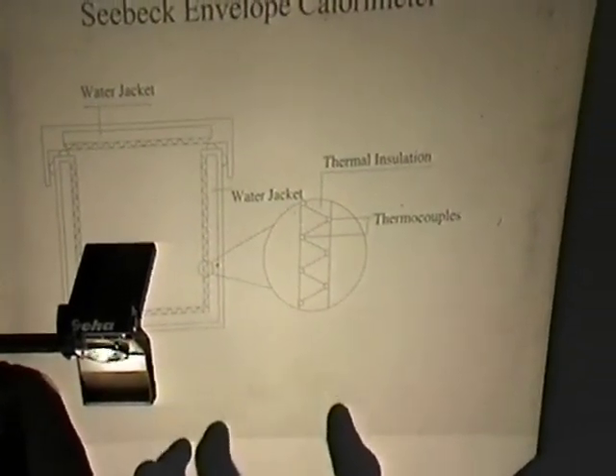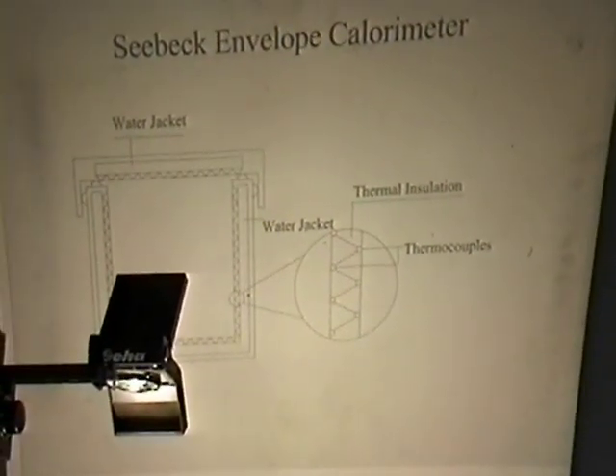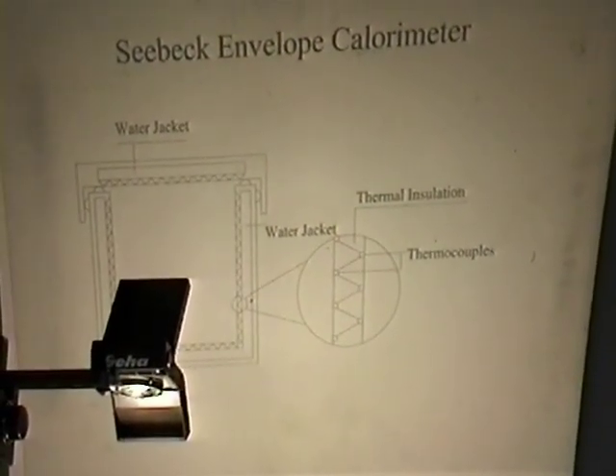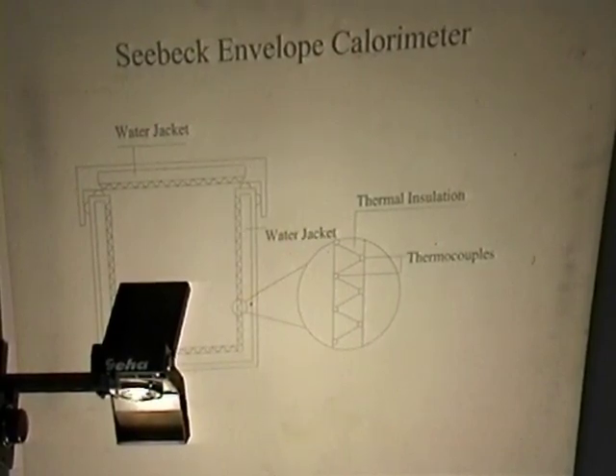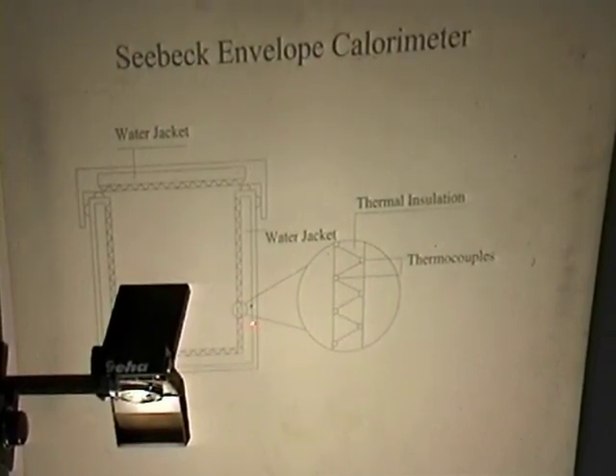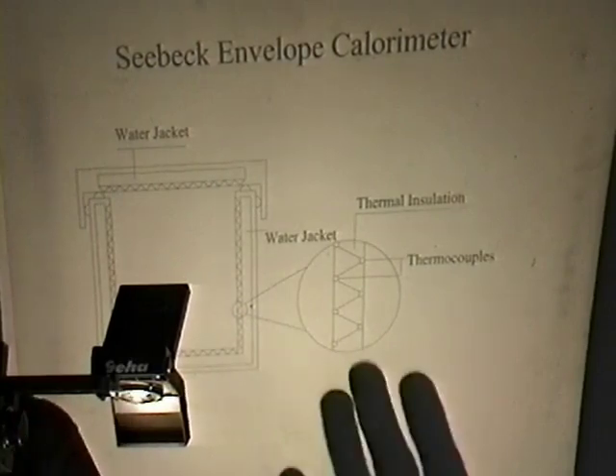Now, the Seebeck envelope calorimeter is a box with several walls. Ours measures 12.5 centimeters by 12.5 centimeters by 12.5 centimeters. And every 2.5 square centimeters are 100 differential thermocouples. Now the differential thermocouples measure the heat flux between the inner cavity and the water jacket of the SEC. If the inner cavity is the same temperature as the water jacket, there's no signal, no flux. If the inner cavity has a higher temperature than the water jacket, then you get a positive signal out.